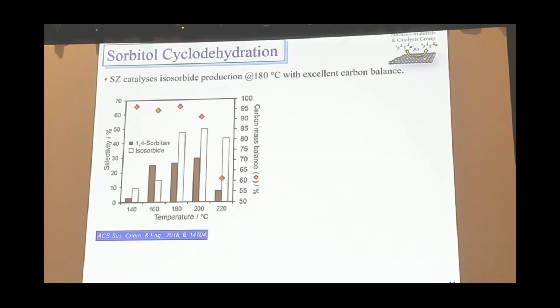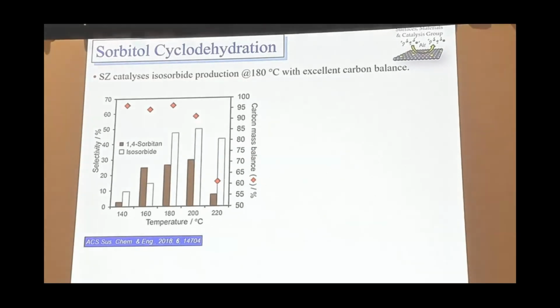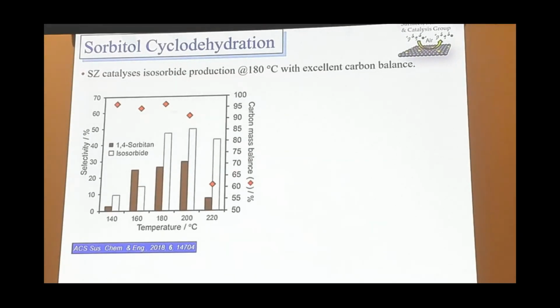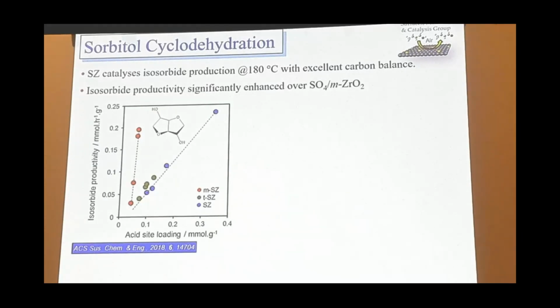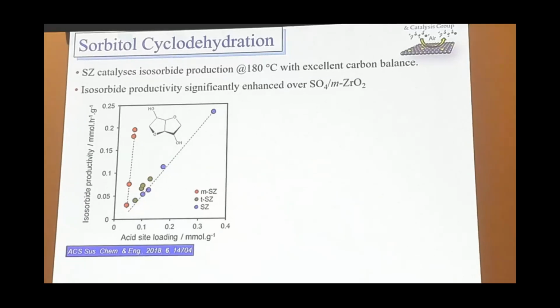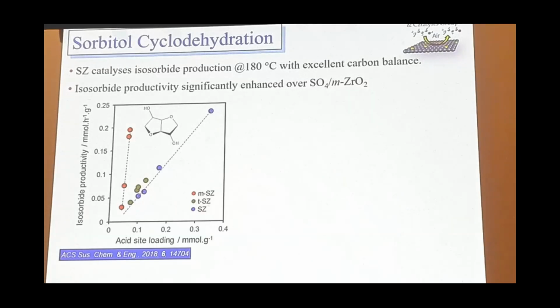When you go above about 200, you start to undergo lots of side reactions, deactivate the catalyst, and you can see that you get a poor mass balance. The operating temperature is around about 180 degrees. If we look at different phases of zirconia used to produce the active catalyst, you can see that the green and the blue, which essentially are tetragonal zirconia, starting from amorphous zirconium hydroxide and calcined to a tetragonal phase, all lie on the same line for acid site loading, and so they will behave very similarly.